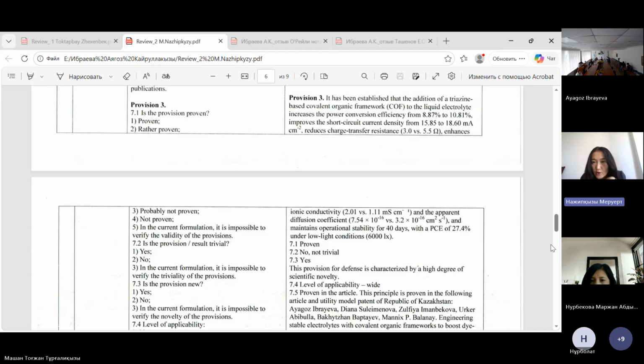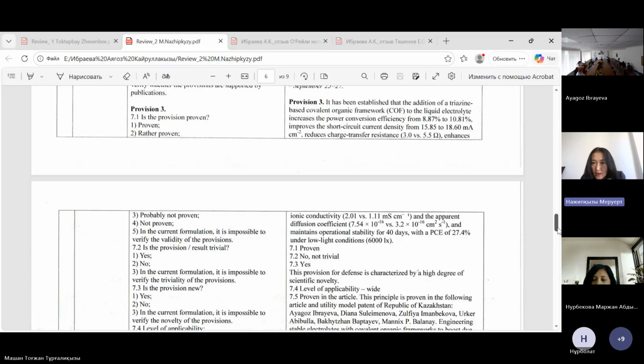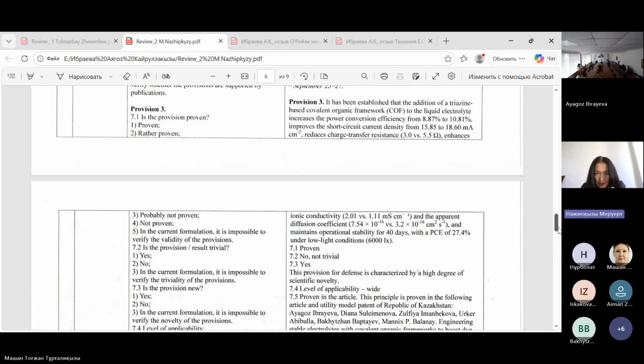3.0 versus 5.5 ohms, enhances ionic conductivity from 2.01 to 1.11, and the apparent diffusion coefficient 7.54 to 3.2 × 10^-16 square centimeters per second, and maintains operational stability for 40 days with PCE of 27.4% under low light condition, 6000 lux.